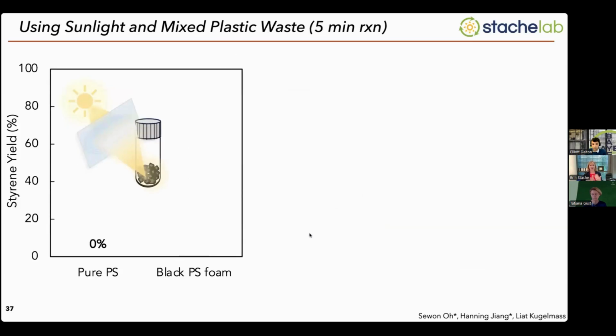Now, we wanted to see if we could use essentially zero energy input or zero electricity input into these systems, because with the LEDs, we're still plugging into the grid. And so what we did is we wanted to see if we could use sunlight, focused sunlight in particular, to depolymerize these existing black plastics. So what Hanning did is she took first pure polystyrene, focused the sunlight with a Fresnel lens or a magnifying glass, if that's what you have. And what she saw is that the polystyrene melted, but nothing else happened.